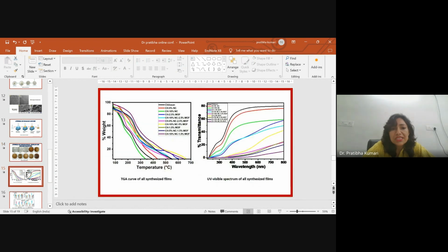So first of all, you can see the TGA graph of all these films. These films are not stable at high temperature, but at room temperature or at a temperature less than 100 degrees Celsius, we can use these films for packaging application. These are quite stable at room temperature, so we can use them for packaging at room temperature. And in the next figure, we are showing the UV visible spectrum of all the synthesized films. Like our focus is only the UV radiation.